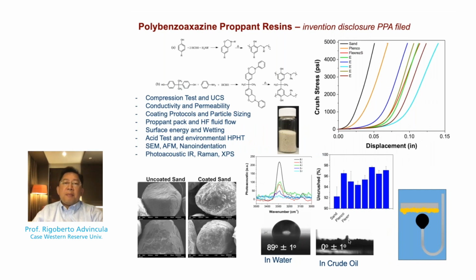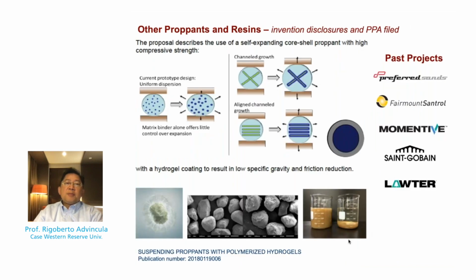So the polybenzoxazine can be coated directly on the particle. Once it has been coated and heated, you basically form a very hard shell. And we have tested the performance of this proppant coated with polybenzoxazine using crush stress measurements and also unconfined compressive strength measurements, and investigated their wetting properties using contact angle measurements, as well as measured the thickness using photoacoustic IR. And we have shown that these proppants and resins have quite a high crush resistance.